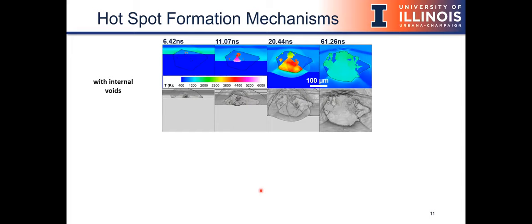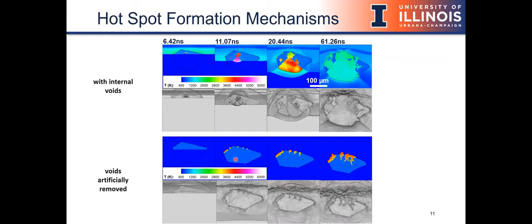In the second frame, we see that there are more of those blast waves from those collapsed voids and the potential for them to be interacting with each other. In the later frames, we start to see the deformation and fracture of the crystal. It was really interesting to think about how these blast waves could be interacting. We were also curious if the crystal would react if there were no internal voids. So Chauvin artificially removed those voids to see if there would still be reaction. For this particular geometry, we did still see surface reaction, which was really interesting because in some other samples at the same particle velocity, we did not. What's interesting is that if you zoom in here, you can see some shock reflection and shock focusing leading to some shear banding. That's really interesting to think about in terms of the single crystal experiments I showed earlier.